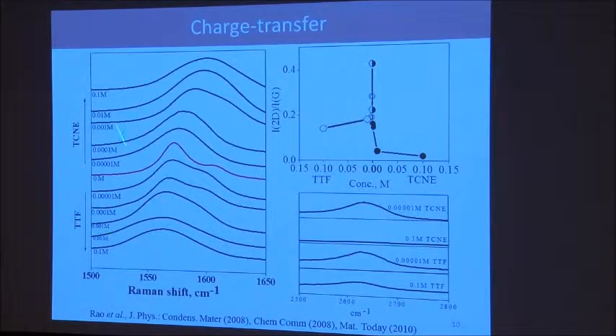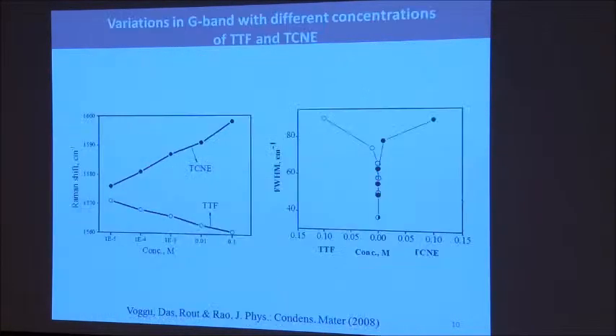These effects on graphene are very significant, very interesting. For example, when I put tetracyanoethylene, the shift of the Raman G band with the tangential mode is extraordinarily large, nearly 20 cm-1, which is a very large shift as you go on doping, putting molecules like TCNE on the surface of graphene.